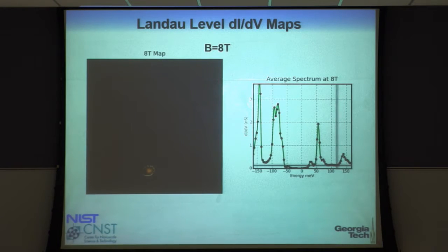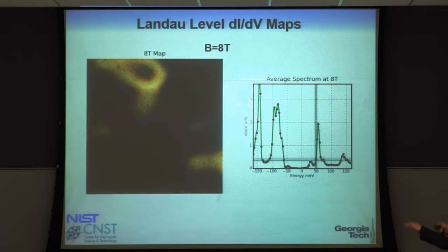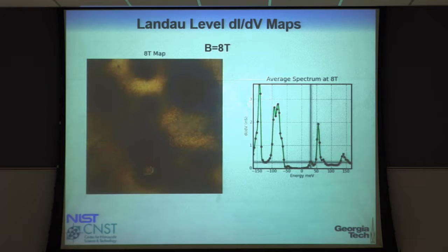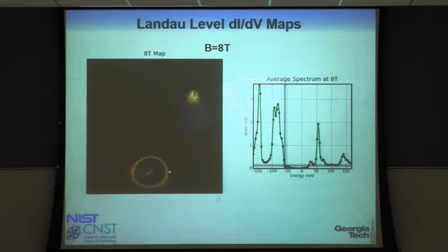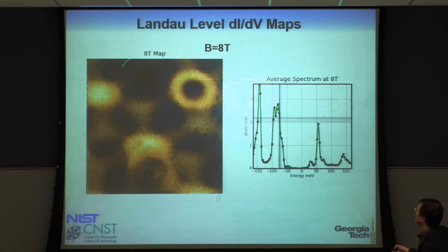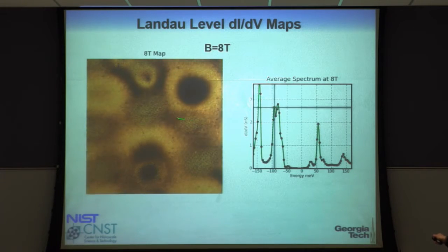Okay. So this is just sweeping to different energies. And every time it goes over this peak, these quantized states, okay? So this is the average spectrum. It sweeps over the state, and you see this enormous spread in the density of states. It spans the entire sample. But before it spans the entire sample, if you look very carefully in these lower areas, you'll start to see rings develop as it goes up the edge of this Landau level. More rings. And then the rings sort of invert. They become dark and go on the downside, okay, until it becomes black.